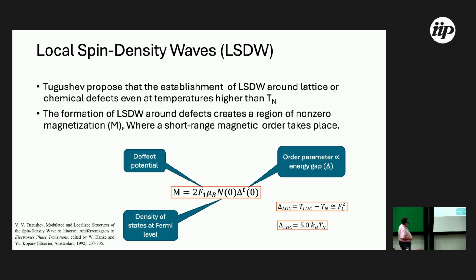Tugushev proposed that the magnetic moment depends on the defect potential, the order parameter delta T associated with the energy gap of the system, and the density of states. And Tugushev predicts the local temperature where local magnetic moments disappear. Imagine the sample: the charge density, spin density wave is equivalent to the sea of electrons in the sample. When the spin density wave state disappears, it is around the defects, small defects, one vanadium atom for example. Around this vanadium atom, in this condition, it is possible for a spin density wave to exist. However, when temperature increases, this behavior disappears.